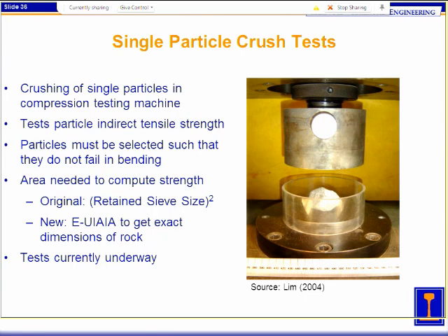One of the reasons we're doing this is, A, we might like to look for more correlations with strength results or such. The second reason, and this is my own personal goal, is what I mentioned earlier with regard to the LAA tests: they were not showing a good indication of strength. The hard part is finding something that will correlate with field performance and can also be run relatively easily. For the shear strength tests, there are not too many of those machines around, and they're rather expensive to build, as we're finding out building our new one. Permanent deformation is even more expensive and even longer to run. LAA I don't hesitate to say is nearly useless, as it's not correlating well with field performance. So we're hoping this might show some good correlation with either field performance or just performance in general.